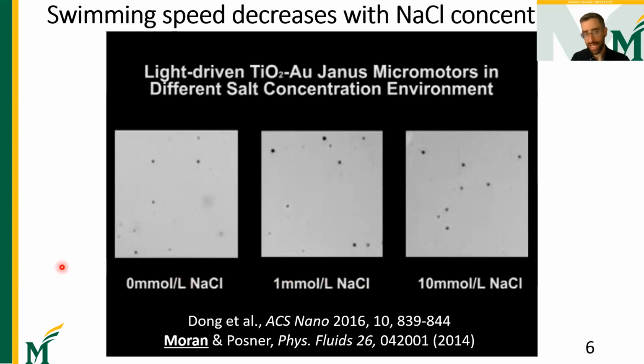Unfortunately, there's a known limitation with particles that propel themselves in this manner, and that is that as salt is added to the solution, the speed slows down. So here, this is from the original paper from Dong et al. What you can see is that at 1 millimolar sodium chloride, the speed is noticeably slower than with no salt at all, and at 10 millimolar sodium chloride, the speed is virtually eliminated. That is, the particles just perform pure Brownian motion.